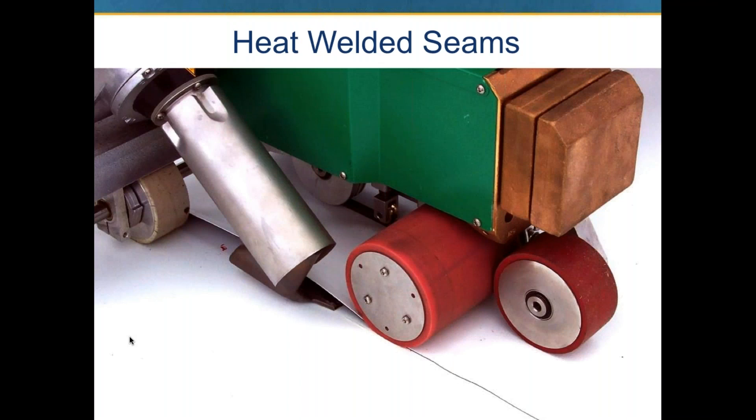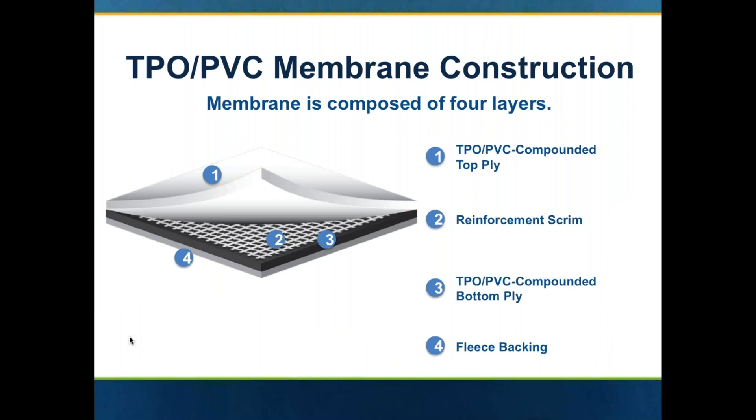It's a very close-up view of a welding machine that will blow air in between adjoining sheets in the side lap. You also treat the end lap and any details. That will blow air at around 1,000 degrees — it will vary based on ambient temperature. Test welds will be made at the beginning of the work session and you'll actually test that to make sure it's welding properly.